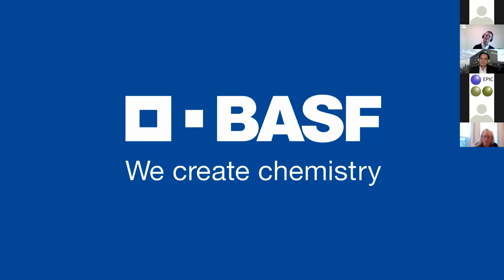Yes. Well, that was maybe too quick. I did not put any UV lacquer 20 years in the sun yet, so I cannot say yes to that. But in the PV, for example, there are accelerated weathering tests which would indicate that kind of stability. It was in a previous presentation also shared as the damp heat test, for example, 85 degrees, 85% humidity. That's one of the tests we also do with our lacquers. And there we have lacquers which withstand 2,000, 3,000 hours of these tests, which is normally the direction you want to go for the PV market.